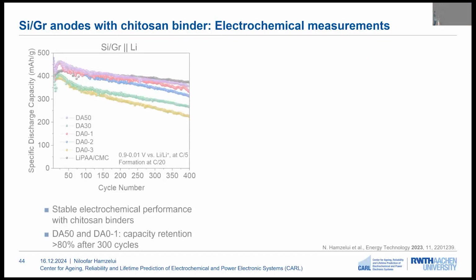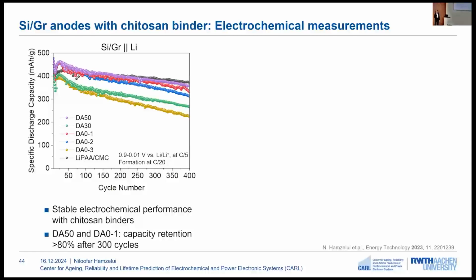After preparing the anodes, they were assembled against lithium metal, and the electrochemical performance of the half cells was investigated. Also, one reference cell with lithium polyacrylic acid and CMC binder using 4-weight% binder was prepared in order to compare it with the chitosan binders. As we can see here in the half cell performance, we can see a stable electrochemical performance for the chitosan binders, especially for the chitosan binders with DA50 and DA01, which are showing a very similar performance to the reference LiPAA CMC binder. And they are having a high capacity retention of 80% after 300 cycles.